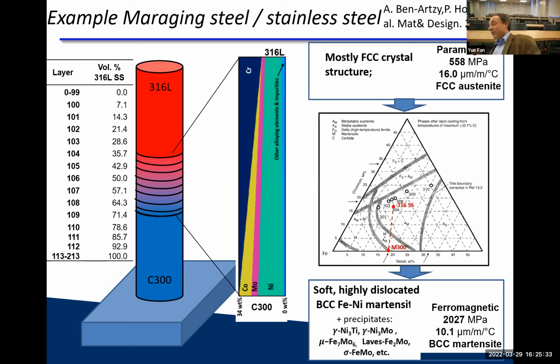It is important to know, however, what the phase diagram looks like when you do that, because you end up with multiple phases potentially. So we plot here the iron, chromium, nickel phase diagram, and we want to go from a 316 stainless steel to a maraging steel. And we chose a straight line. Of course, you could choose other directions. You could increase the nickel content and reduce it again, do some other path if you find that there are some intermetallics on the way. In the titanium world, that's sometimes what people want to do. They want to avoid the intermetallics, but in this instance, it's not necessary. However, you still join a very different FCC material to a BCC material, something with 500-something megapascal strength to 2000 megapascal strength, and very different thermal expansion. So it's a reasonably different material.